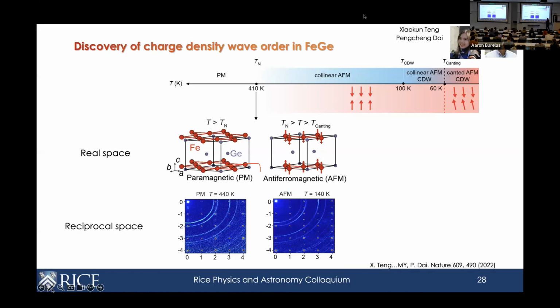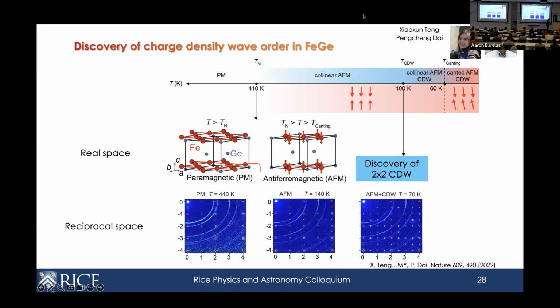Fine, this is great. But they just kept cooling down, and when they did, across 100K, they saw all of these interesting new peaks appear. This was actually a very surprising finding because they were not expecting it. You can see there are all these additional peaks that appear, and they can analyze the intensity. I won't go into the detail, but they can conclude that these are not magnetic peaks, they're structural peaks, and this is the discovery of this 2x2 charge density wave in iron germanium. And this is very strange.